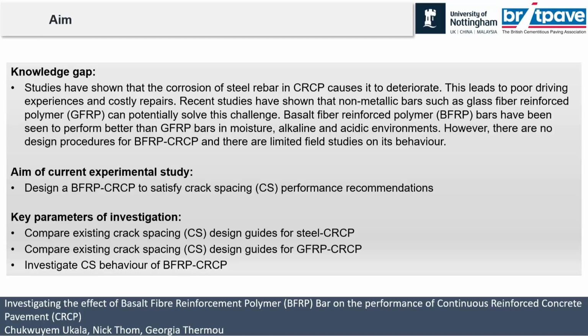What is the potential of using BFRP? When I say BFRP, I mean the basalt bars, in CRCP, and I'm going to check that in 3 key areas. So first, I'm going to look at the behavior of the CRCP made with steel, the crack spacing of the CRCP made with steel. I'm going to compare existing crack models to do that. I'm also going to look at the CRCP made with models calibrated using the glass fiber reinforced polymer, because the glass fiber, as I said, is a bit more important. And also I will now investigate the potential of having a basalt fiber reinforced polymer in CRCP, all towards reducing or minimizing or at least managing the crack spacing of the CRCP using this non-metallic bar.